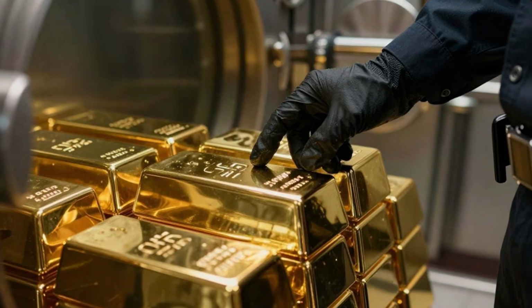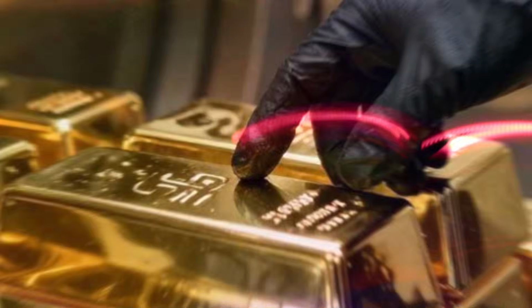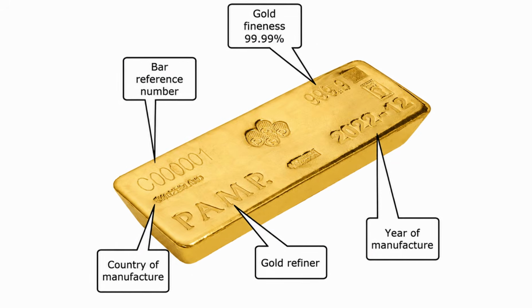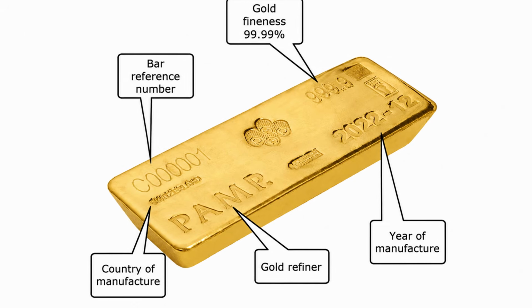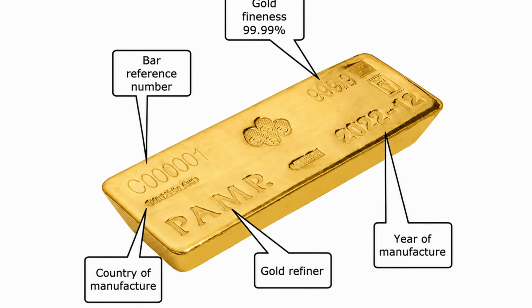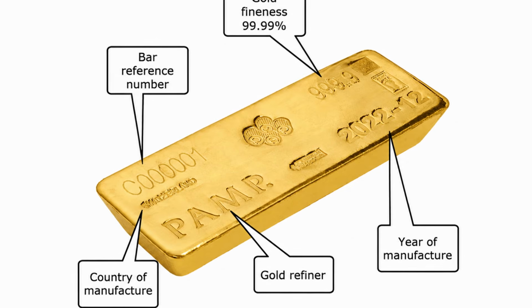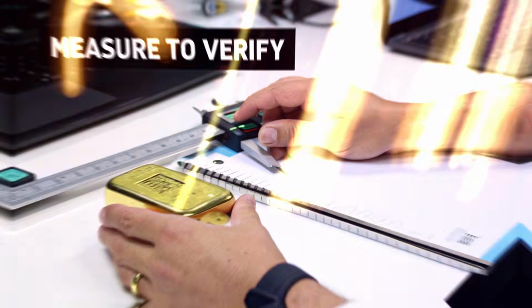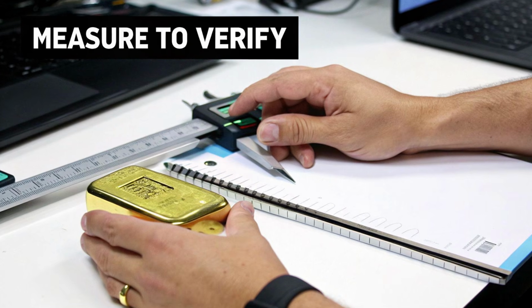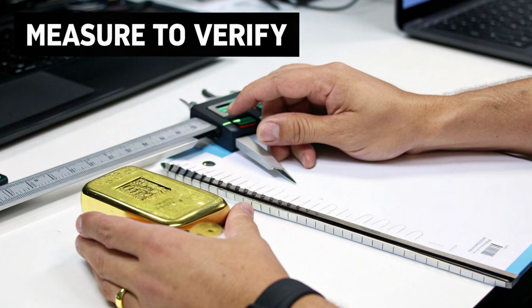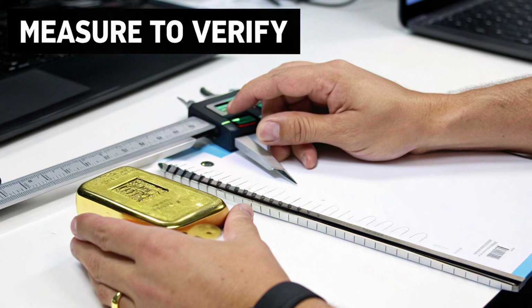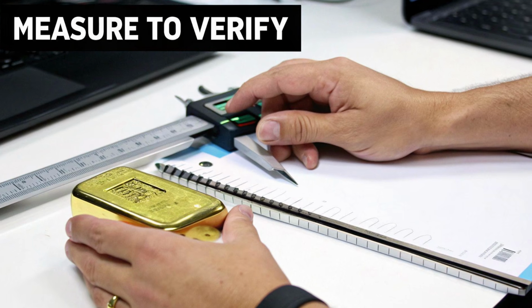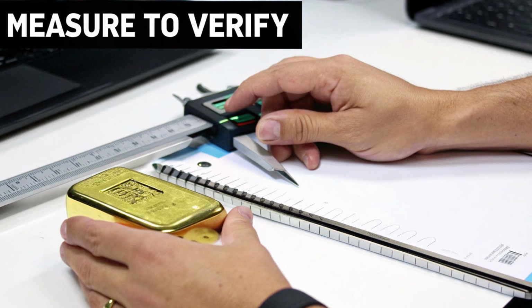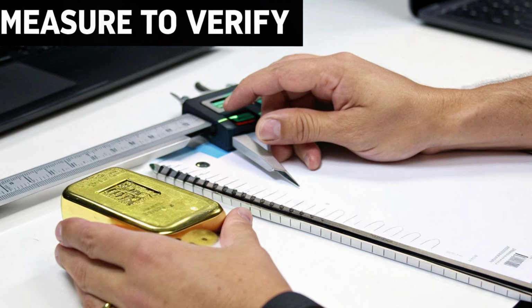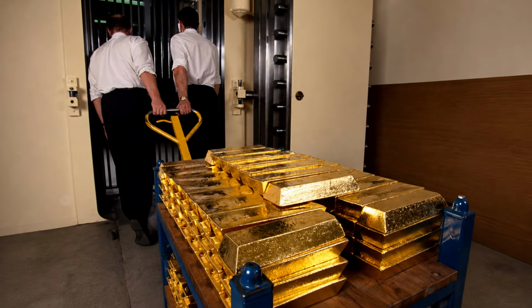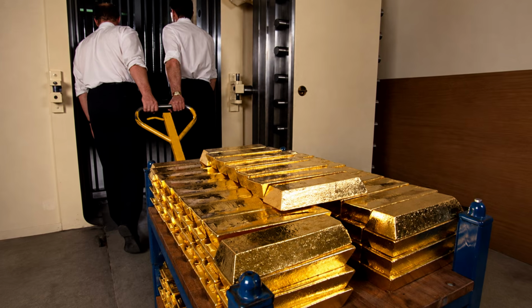A London Good Delivery Gold Bar is often called a 400-ounce bar, but it does not need to weigh exactly 400 troy ounces. The permitted fine gold content ranges from 350 to 430 fine troy ounces, approximately 10.9 to 13.4 kilograms of fine gold. Its fineness must be at least 995. Smaller bars can be legitimate products in other markets without qualifying as London Good Delivery. A 1 kilogram 999.9 bar may contain purer gold by proportion, yet still belong to an entirely different product category.